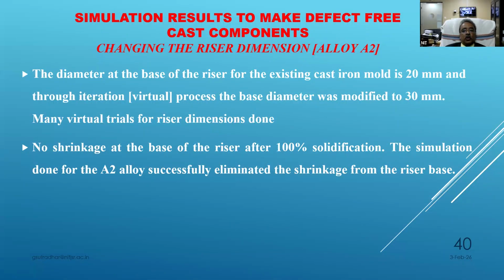This ultimately came from the simulation. When you take 30 mm as the diameter of the base, there is no shrinkage at the base of the riser after 100% solidification. So the simulation was done for the A2 alloy successfully, and it eliminates the shrinkage from the riser base.